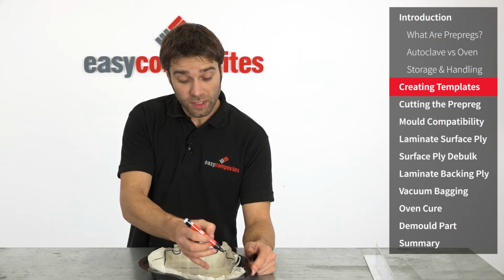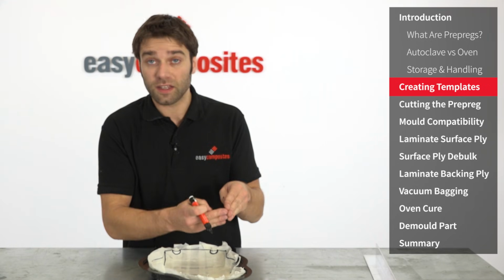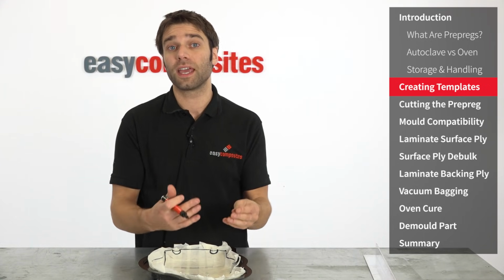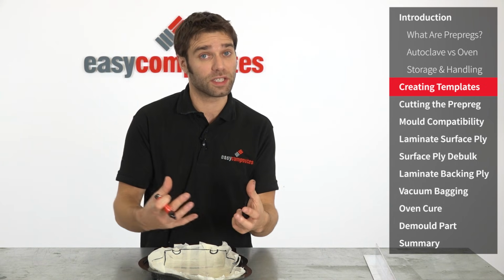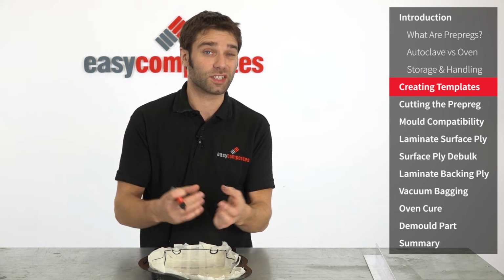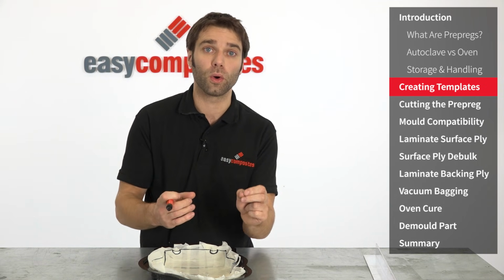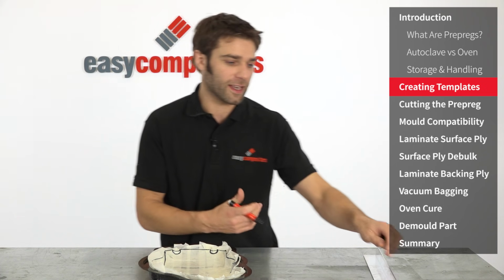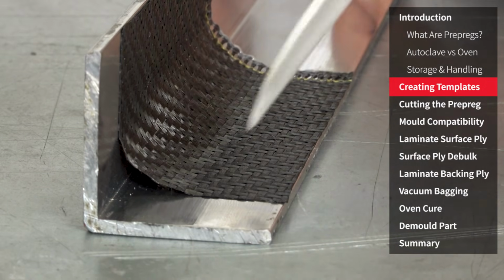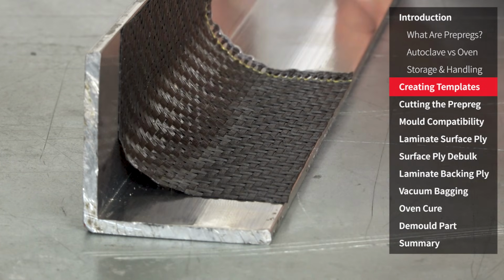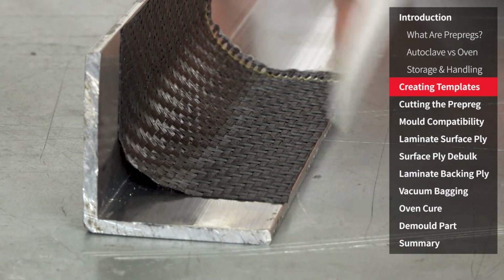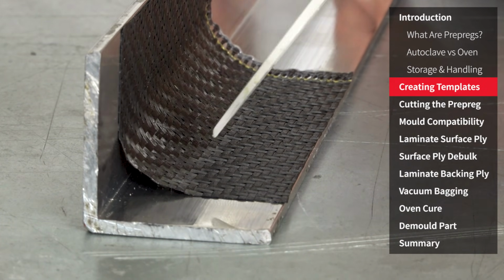The reason why I'm putting cuts down in the negative features in the corners is it actually makes the laminating procedure that much easier and reduces the chances of bridging, so you're less likely to get voids on the corner of your part. I can show you in more detail here. I've set up this small example which hopefully should illustrate how putting cuts in corners and negative features can really help in the laminating stage.